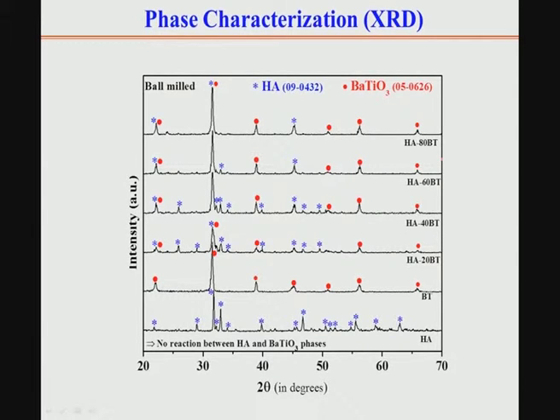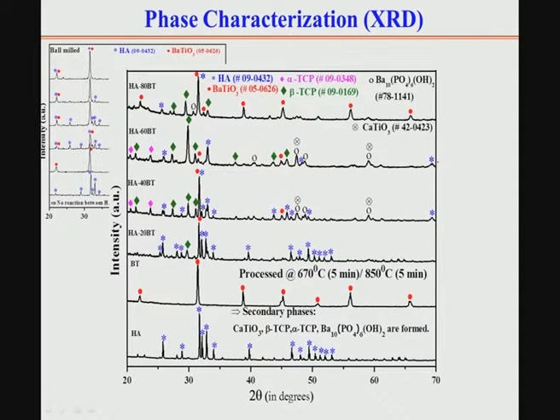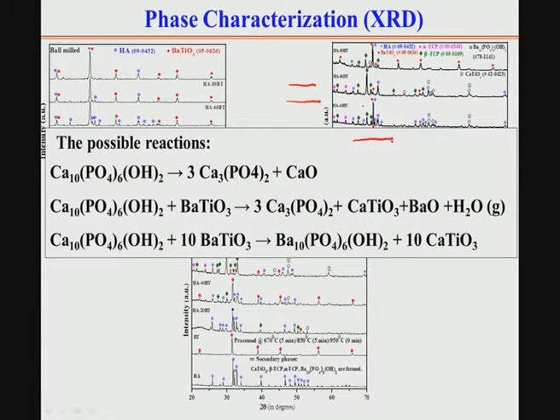Now, we have made this hydroxyapatite barium titanate composite at different temperatures, and after that when we did X-ray diffraction, we saw some minute amount of beta tricalcium phosphate and alpha tricalcium phosphate as well as calcium titanate. So, it does show small detectable amounts of these phases, and then we tried to understand how the formation of this detectable amount of calcium titanate and other phases can be explained.